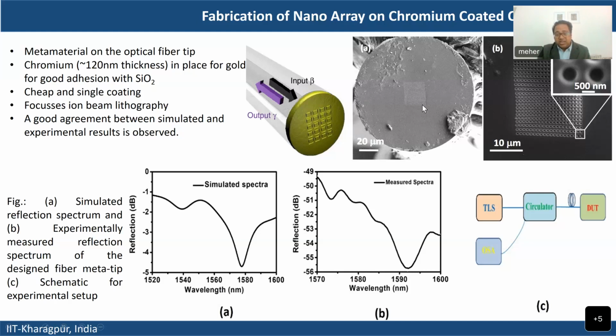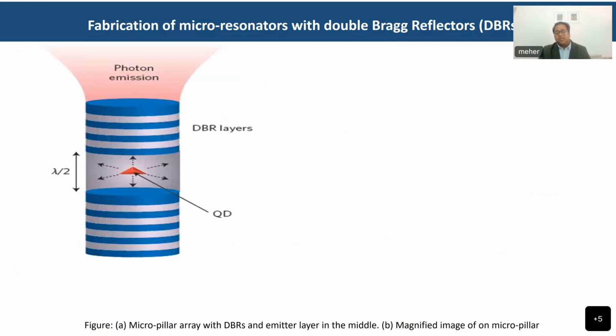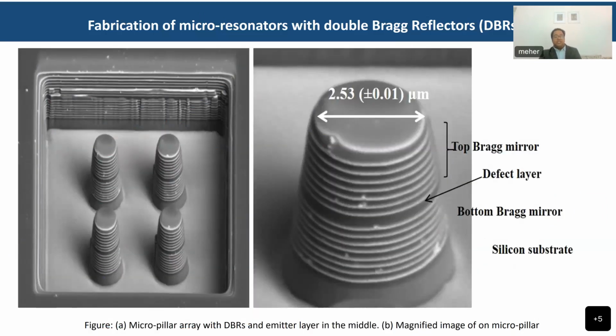And then at the core, we very specifically made the pattern, which is actually in the nanoscale regime. Then we tried to simulate the spectra, and then we measured the spectra. Both spectra are very similar, and we got good sensitivity. Let me show you some other kinds of photonic structures also, which can be used in sensing or other applications.